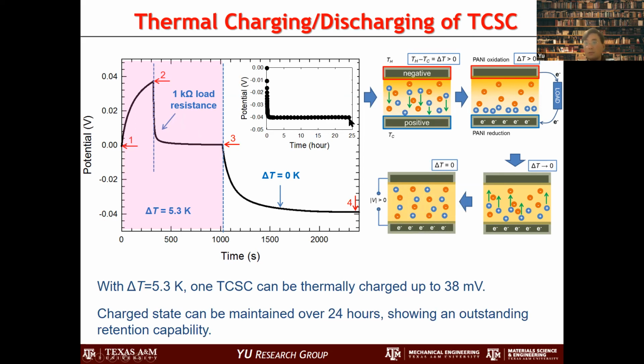So what that means is that we can use this when we need it. So basically, this is how we charge those capacitors using thermal energy rather than electrical input. Okay, that's what we have done. But still, the voltage that we can have with a single device is only 40 millivolt, which is not good enough. And this is 5 Kelvin, which is good for body temperature, but it's only 40 millivolt. It's not that great.